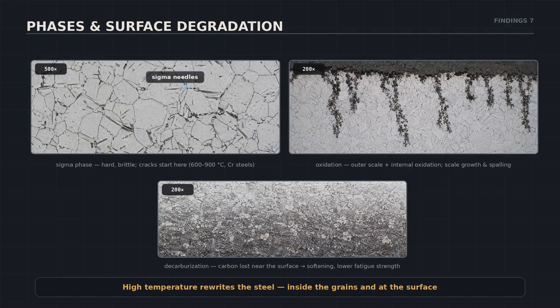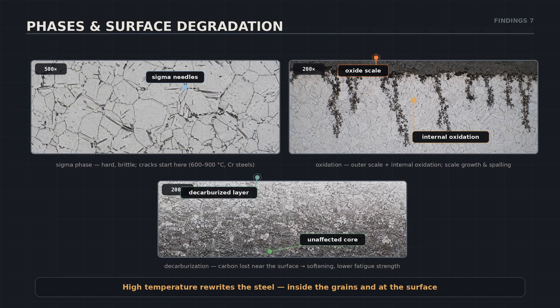Temperature attacks chemistry as well as structure. In chromium steels held between roughly 600 and 900 degrees, sigma phase forms, hard, brittle islands where cracks love to start. At the surface, oxidation builds an outer scale while oxidation penetrates along the boundaries inside. And beneath the scale, decarburization strips carbon from the steel, a soft, weak layer with reduced fatigue strength. All three are visible on a single replica.